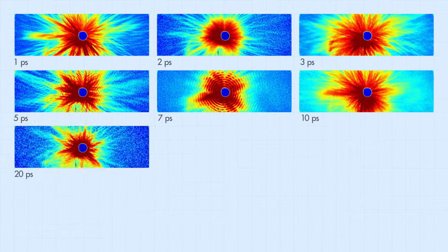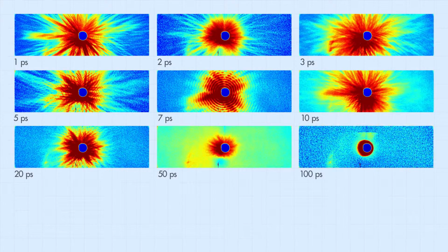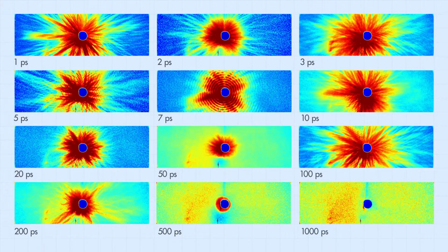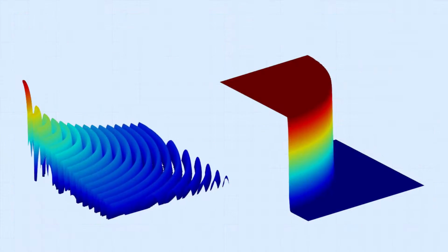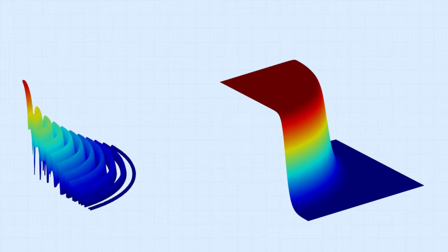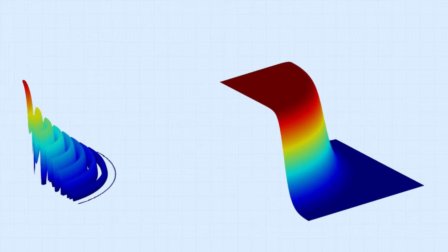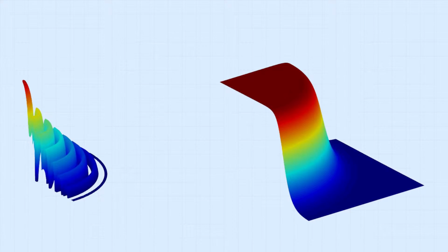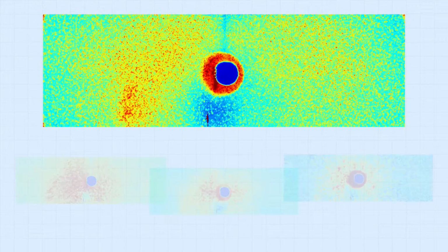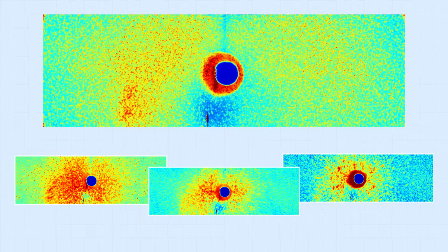As we increased the delay time, the diffraction patterns became blurrier, and we recorded less elastically scattered photons at high scattering angles. Less high-angle scatter is correlated to a softening of the surface when the particle becomes ionized and outer layers explode. This occurs at the picosecond timescale. On the nanosecond timescale, when our ionized particle has recombined to neutrality, speckles appear in the diffraction pattern.